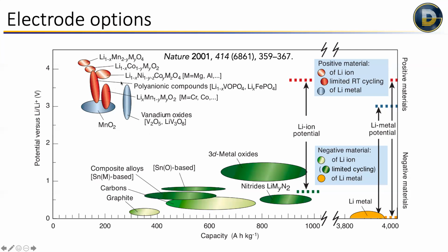Whereas the positive electrode materials, there's a whole bunch of different ones. I'm not going to get into specifics there right now, but I will point out that we're using graphite right here. That lithium metal, which was the highest point on the plot of the different types of battery, is all the way out here. So it's around 10 times as much lithium capacity per kilogram as graphite is. So if you could make lithium metal work, pure lithium, there's a big upside here versus graphite.